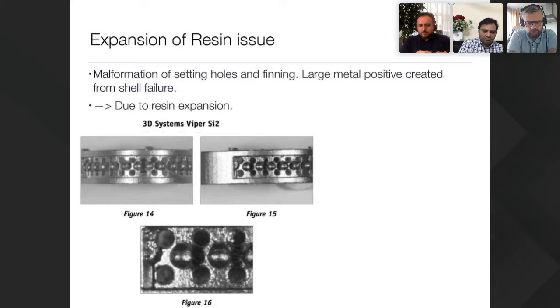Let's see another point about the expansion of the resin. This is another paper, I think we have it in the reference, it's quite old, maybe 10 years. Some of you may know the 3D Systems Viper machines, they used this resin. Because the resin is expanding in that case, you can see on figure 16 some large metal positive areas that were created because the ring expanded during burnout. So while expanding, it cracked that area of the investment, and that investment is gone—instead of investment, now you have metal taking its place. This kind of issue is really related to the expansion of the resin. So you need a low expansion resin.